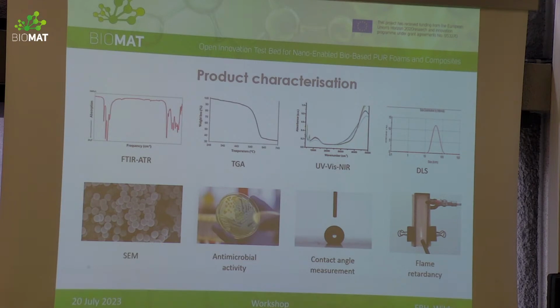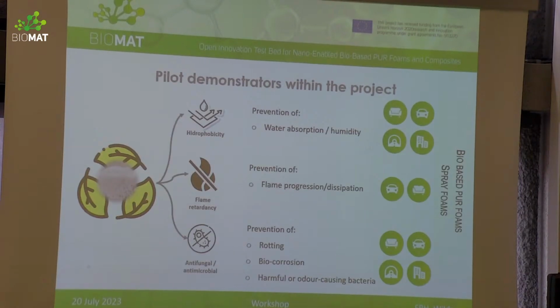The obtained particles are then characterized by infrared spectroscopy, thermogravimetric analysis, ultraviolet, visible and near-infrared spectroscopy, and the size and morphology can be assessed by dynamic light scattering or electron microscopy. We also perform tests of interest, such as to assess the antimicrobial activity, the water contact angle measurement, and of course the flame retardancy properties.